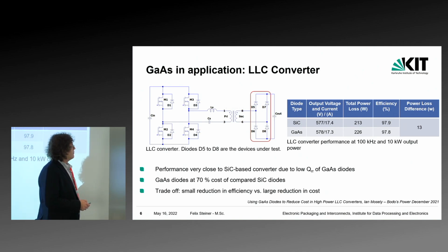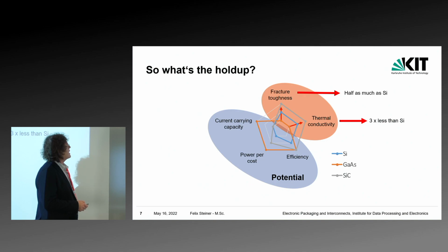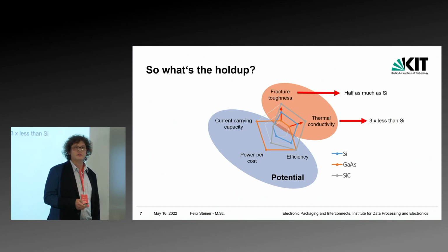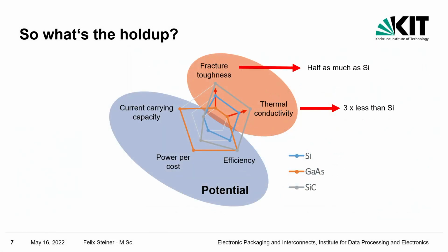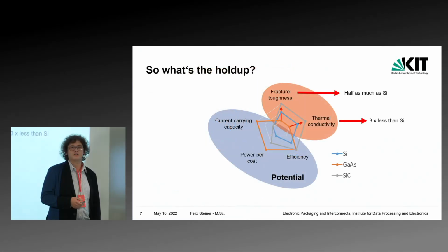So, what's the problem? You get a quite high current carrying capacity. You get a nice power per cost, and also a good efficiency, comparable with silicon carbide. But then there's the thermal conductivity, and that's 3 times lower than that of silicon. And compared to SiC, it can't compare. And also the fracture toughness is even worse than that of silicon.